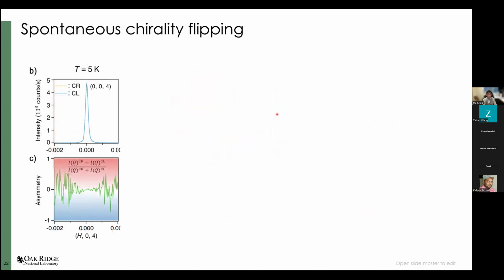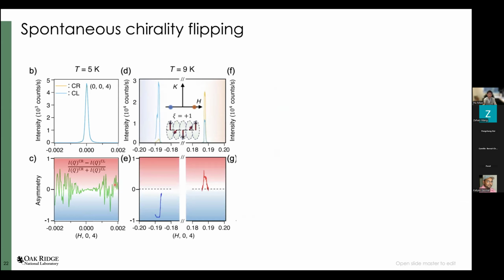So now we can move on to the experimental data. We first test our experimental technique on the structural Bragg peak. Not surprisingly, there's no circular dichroism at all because it's a structural Bragg peak. Once you move to the magnetic superlattice peak, now you can see the positive circular dichroism on the positive Q, negative circular dichroism on negative Q. That basically means at 9 Kelvin, the magnetic domain has positive chirality.